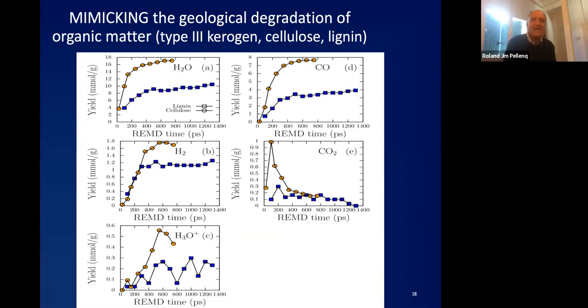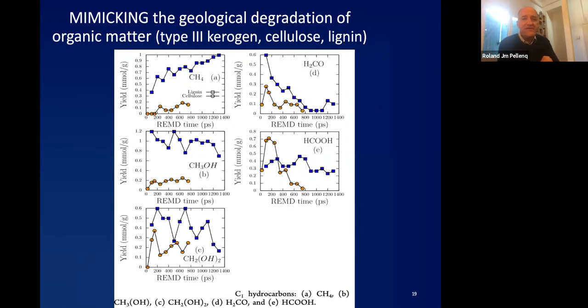Clearly, lignin, these are the squares, for instance, and cellulose are the circles. We produce less water with lignin than cellulose, less CO with lignin than with cellulose, and so on. Okay, and this is typically linked with the structure of the pristine molecule in the first place. All right, so then we can go further with different molecules, and obviously the methane is very, very interesting, because we see this time that actually with lignin, in the squares, we produce way more methane than cellulose. Cellulose is not good shale gas, if you want. All right, lignin is way better, for instance, just to tell you that.